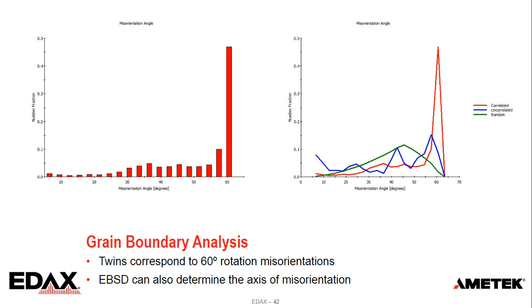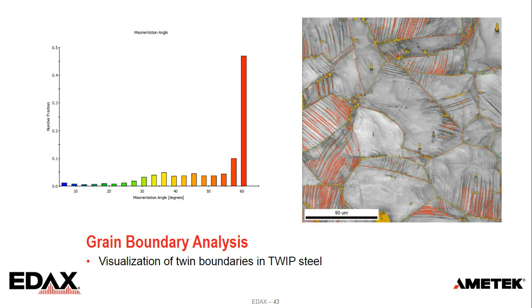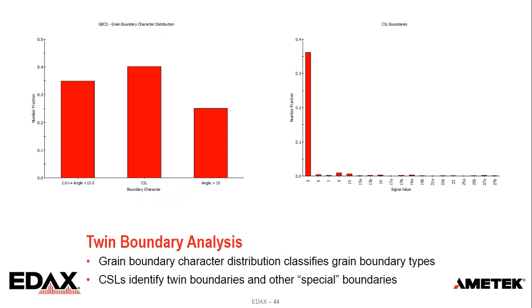And again, like we did previously, we can highlight these. With color highlighting, we see the twin boundaries come out in red, as we'd expect. And we can characterize all the boundaries in there. The plot on the left shows our GBCD, where we have low-angle boundaries, CSL boundaries, and high-angle boundaries, and we can get an idea of which is which. The distribution on the right characterizes CSL boundaries by what's termed sigma values. CSLs are a boundary model showing the frequency of shared lattice sites between two different lattices for adjacent grains. In this case there's a high fraction of sigma 3 boundaries. Sigma 3 corresponds to those 1-1-1 60 degree rotations. But we can also see there's a small peak at 9, which would be a twin of a twin boundary. So we get a lot of information about grain boundary character with EBSD.